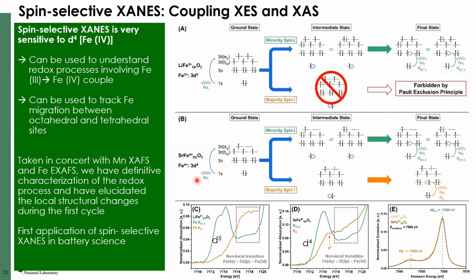On the other hand, if you have Fe4+, assuming an ionic model, and you do the same thing, either take the up spin or the down spin, in both cases you will be able to do it because this level right here is empty. It does not have this one up spin over there. So one should be able to put both the down spin as well as the up spin electron. One can do this by tuning the energy of the X-ray to exactly this transition where you go from the 1s level to the 3d level. And if you look at the spectra that comes out, in the case of Fe4+, let's start over here. You will see that there is a feature over here.